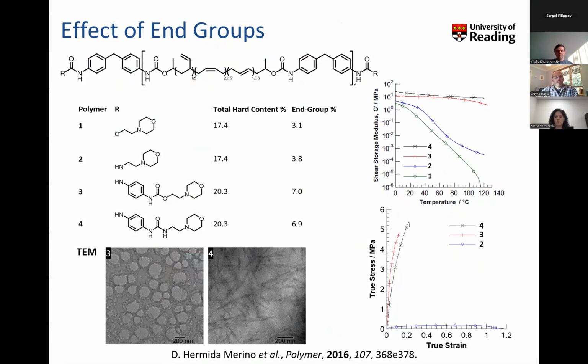Now, the other thing that we've done, again with our synthetic hats on, is we've varied the end groups. If we increase the hydrogen bond density by having two sets of ureas separated by a benzene ring, we have a very strong hydrogen bond association, which we can see through the aggregates indicated by TEM. But what is also quite clear, as shown by the shear storage modulus in the top right, is that when you have stronger hydrogen bonds, which are more pre-organized, the rheological characteristics are very, very different.